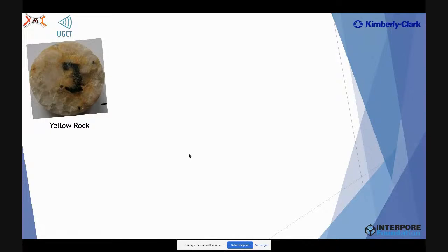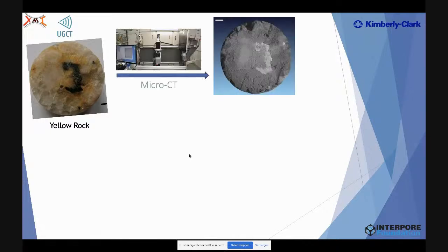So what we did in the past is we took a stone, we first scanned it, and based on the CT, you see that you have different gray values, and those different gray values indicate differences in linear attenuation, so differences in average atomic number and density. But without knowing extra information, we cannot say which mineral is which.